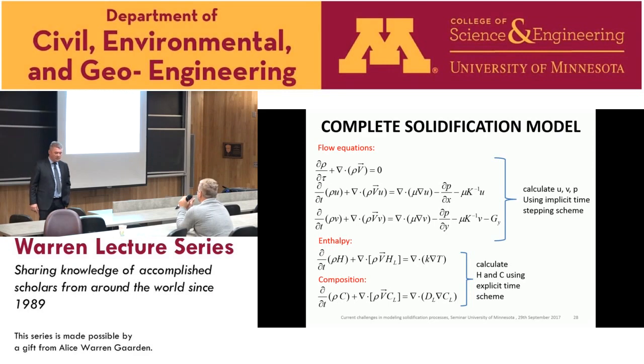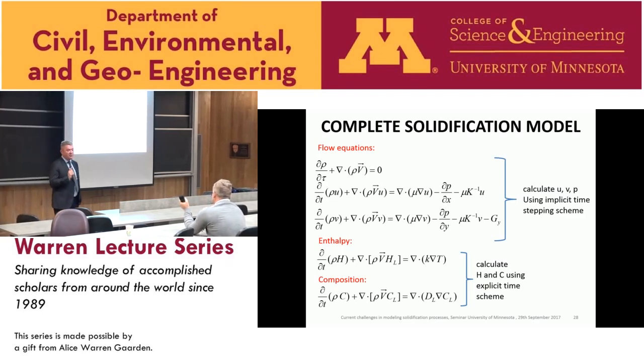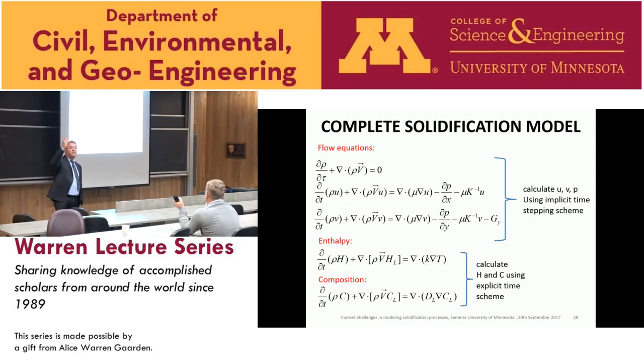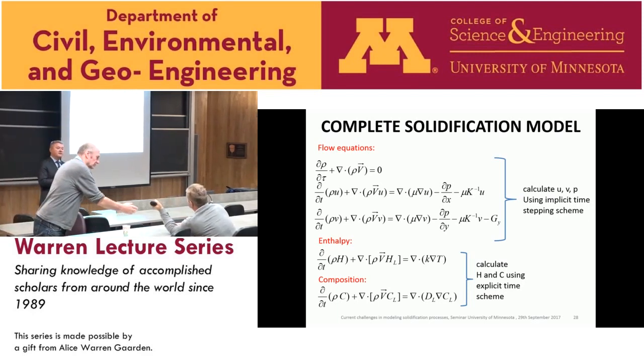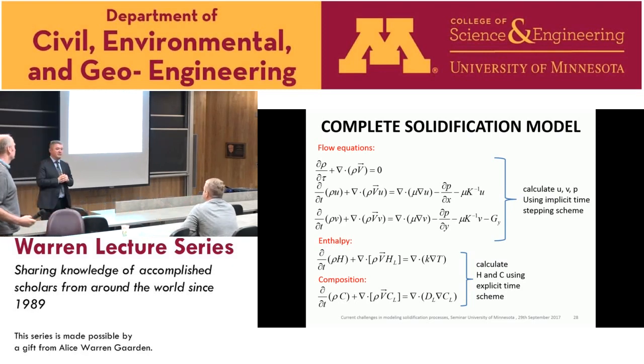We didn't have such a case up to now, but this is a good idea because in the real cases of metal alloys, there is turbulence because when you have a casting, the piece that you cast is a couple of meters, and you have a turbulent flow. What I saw so far is that they take care of turbulence by increasing the viscosity. When you deal with alloys or multi-component systems, you don't need to have a smooth transition, like in a pure substance. The difference between the TL and TS can be tens of degrees Celsius, let's say 60, 40, 50, whatever. But it's a good point about pure substances, for instance, for water.